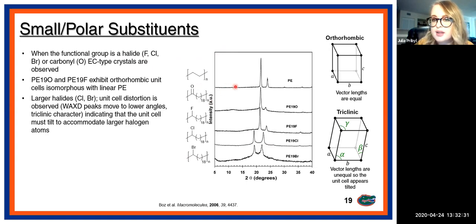So the top one is linear polyethylene, which has a well-known orthorhombic type unit cell. That's a really symmetric unit cell, and there's an example of one here where all the vector lengths are equal. And as you incorporate a carbonyl and a fluorine group, we notice that the location of these X-ray scattering peaks doesn't change a lot. And what that tells us is that the unit cell is also orthorhombic, like linear polyethylene.